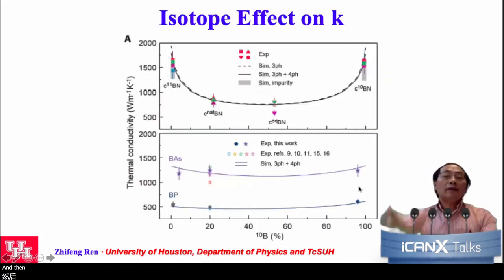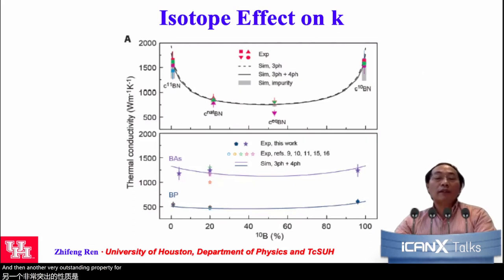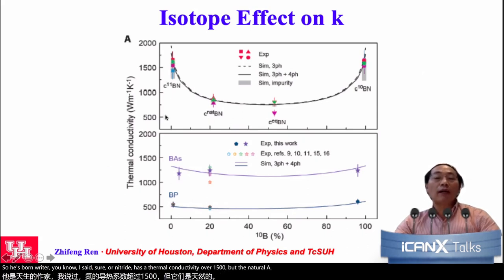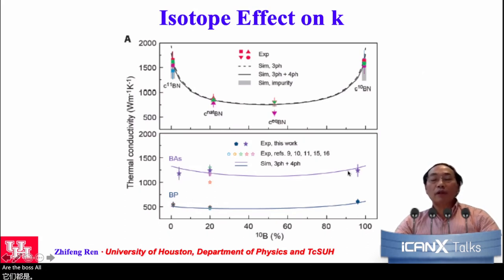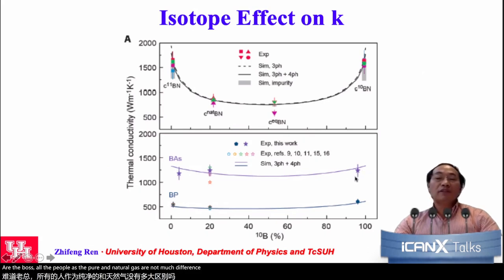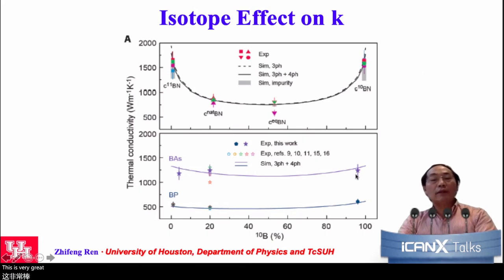And then another very outstanding property of boron arsenide is the isotope effect. As we know, diamond has a very strong isotope effect. So does boron nitride. You know, isotope pure boron nitride has a thermal conductivity over 1500, but with natural boron the thermal conductivity drops below 800 watts per meter per kelvin. But boron arsenide is very outstanding. Between the isotope pure and the natural boron, there is not much difference. The difference is less than 10%. This is very great news for future applications because the price will be so much lower if it does not require isotope pure boron. So that's very good.